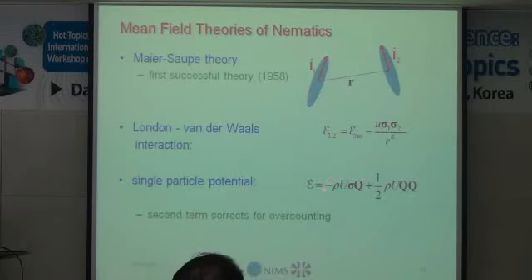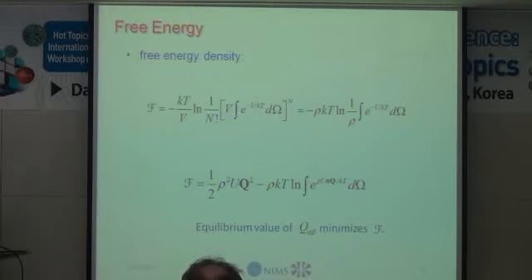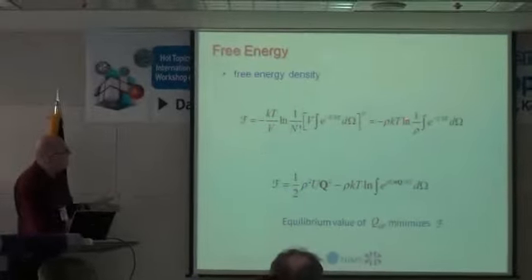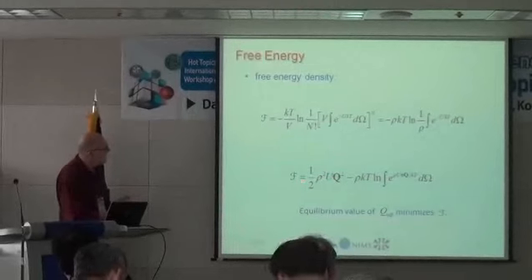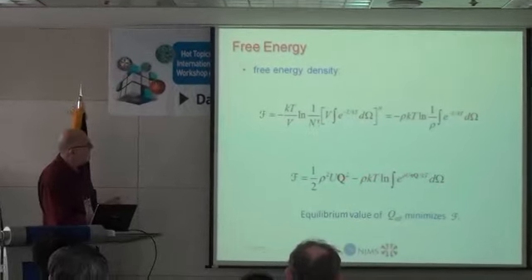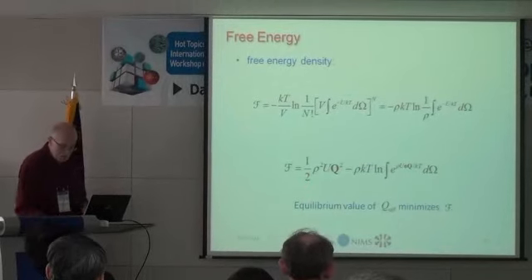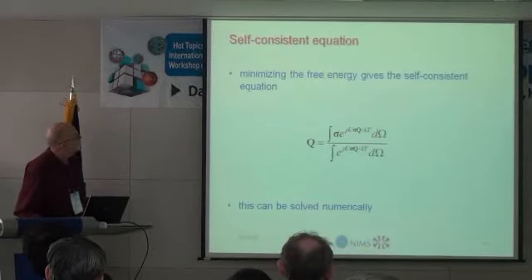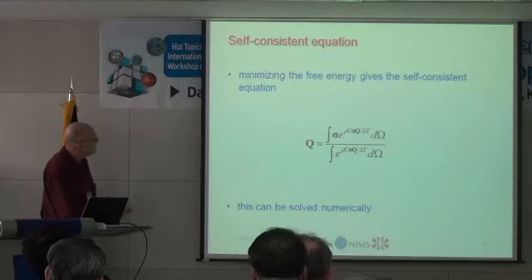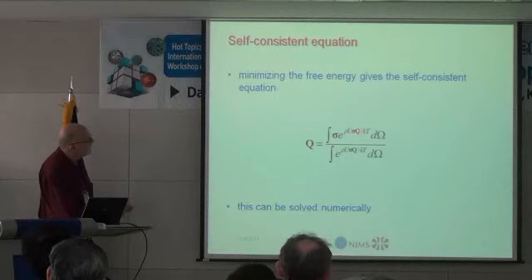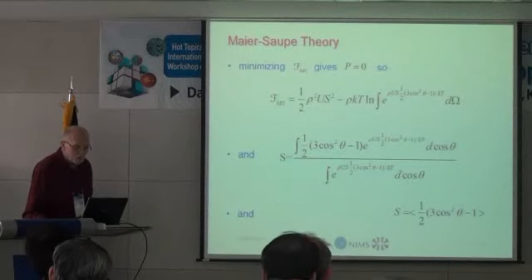So this is the single particle potential in Maier-Saupe theory, and this term has to be subtracted to correct for overcounting. So this is just a consequence of looking at pairwise interactions. And then once one has the energy, one can stick it in here and then immediately derive the Maier-Saupe free energy in terms of the order parameter tensor, and then minimizing this gives the equilibrium value of Q. So one then gets a self-consistent equation, so this order parameter appears both here and here in the exponent, and then one can solve this numerically.